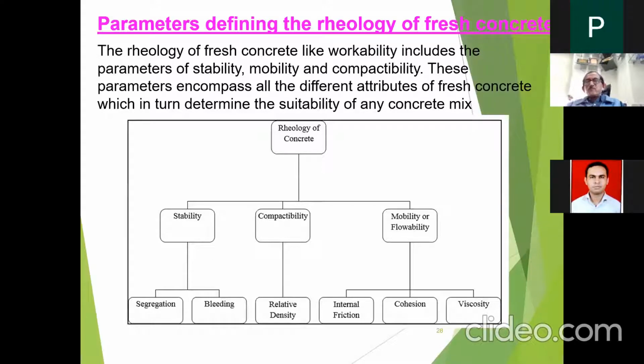All these parameters are played with when self-compacting concrete is designed, by addition of paste and by addition of viscosity modifying agent. So we are playing with the internal friction. We are adding a lot of superplasticizer, or I would call it a hyperplasticizer, so that internal friction is reduced. Then we have a proper mix design, properly graded material, and water-powder ratio so that bleeding and segregation are not there. The mix should be cohesive, but not too cohesive, otherwise it will hamper the workability. And it should be viscous enough so that it can be molded into shape.